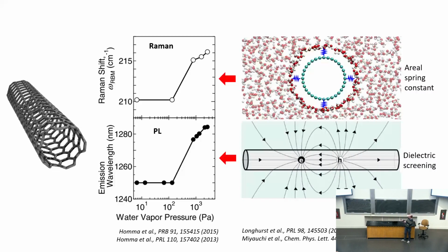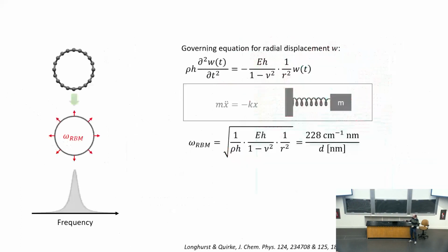For Raman, the physics is very different. When you have fluid present on the outside, same as on the inside in terms of the physics, it couples by van der Waals coupling to your CNT wall, and that coupling will change a specific breathing mode frequency that we can read out in Raman spectroscopy. Here is how this can be understood mathematically. This is the governing equation for radial displacements of the CNT. It looks pretty much like Hooke's law, and when you solve Hooke's law, you get a frequency. The frequency depends on the inverse of diameter. That's pretty well known for this mode.